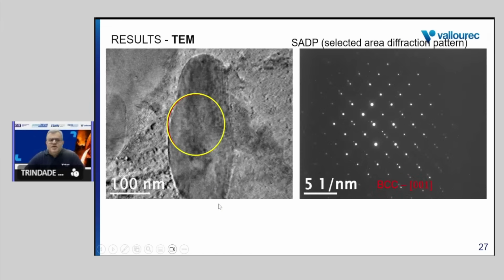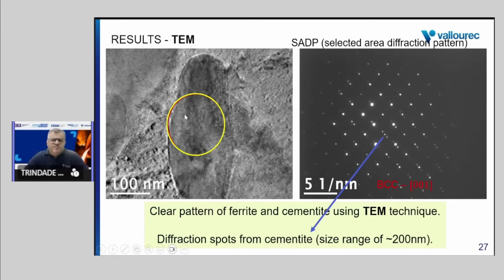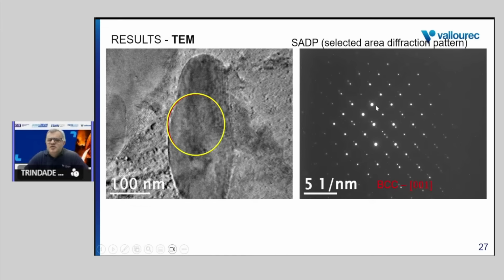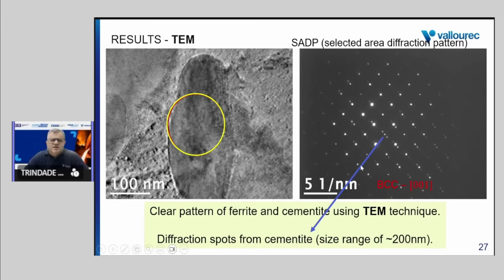Also, here you can see, just as an illustration, when we take this selected area diffraction pattern using TEM, we see clearly the ferrite pattern and also the diffraction spots from cementite. In this case, the cementite crystal size is around 200 nanometers, just as information.